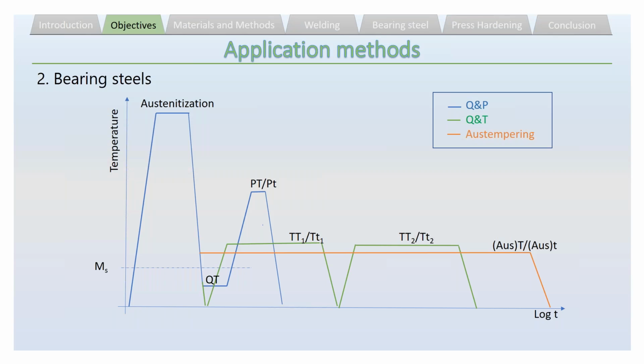The other method to produce bearing steels, which is new, is austempering, which results in carbide-free bainitic steel. This kind of structure is really good. It could have very high toughness and very good strength at the same time. But the point is that it takes several hours, or we can say several days. So it's difficult to produce such a structure because it's costly and time consuming. The idea of this work was to design the chemical composition in a good way so that we could use quenching and partitioning for just a few minutes. And we have tested this.